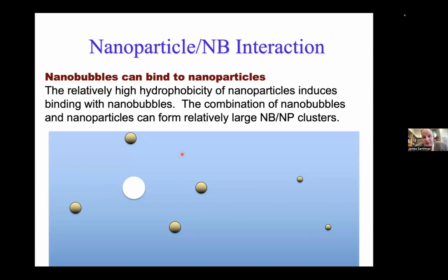Anyway, what I was really interested in was not so much the nanobubbles themselves, but how they interact with nanoparticles. Nanoparticles have a very high surface tension as well. And if they encounter a nanobubble, they will bind to it. The hydrophobic forces can actually overcome differences in charge between the nanobubble and the nanoparticle. In other words, if I have a particle that's -5 millivolts, it'll still bind to our nanobubbles, which are -30 millivolts or more. So this hydrophobic force at this size scale is really powerful.